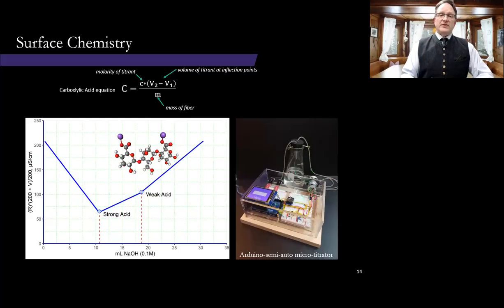So with regards to surface chemistry, the carboxylic acid content that we developed on the surface of our nanofibers was determined by a method called conductometric titration. What we do is we protonate the sample with a strong acid and titrate against sodium hydroxide. During the titration, the first inflection point is our strong acid. The second inflection point is our weak acid. And for ammonium persulfate, we have a very challenging inflection point to measure.